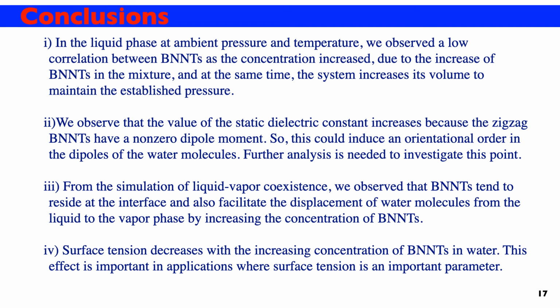Finally, our conclusions are: in the liquid phase, at ambient pressure and temperature, we observe a low correlation between nanotubes and water as the concentration increases, due to the increase of nanotubes in the mixture, and at the same time the system increases its volume to maintain the target pressure.